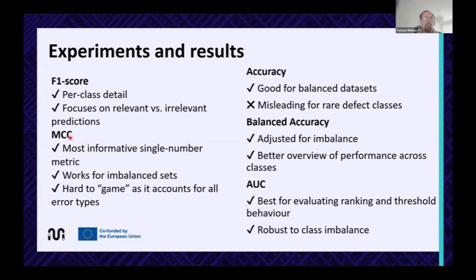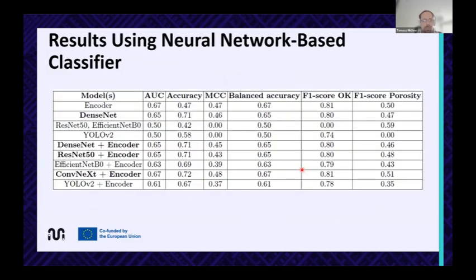The Matthews coefficient is also quite good for dealing with imbalanced data sets. So this was quite good for getting the real information on how the performance looks for the classifier in a bit imbalanced data set. Yes, accuracy in this case was not the best because it's good for balanced data sets, but not so well for the imbalanced ones. And also balanced accuracy and AUC are quite good for imbalanced data sets, and each metric works a bit differently. So we can have different ways of getting information on how the model is performing.